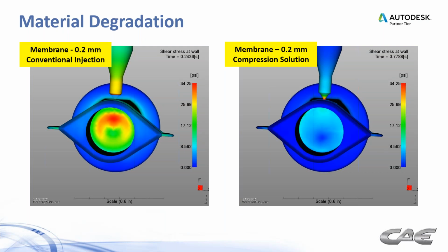So one of the things that you have to pay attention to when you're dealing with thin walls is material degradation. So on this same part here, if we had gone with conventional injection and we were able to fill it, you see the elevated levels of stress there that are caused by the injection process in conjunction with the thinner walls. So thinner walls means a higher amount of molded in stress. And when you have a higher amount of molded in stress, that's telling you that the manufacturing process is affecting the part quality. It's affecting the, again, the assumptions that are made about the material properties when you look at a material data sheet, for example.